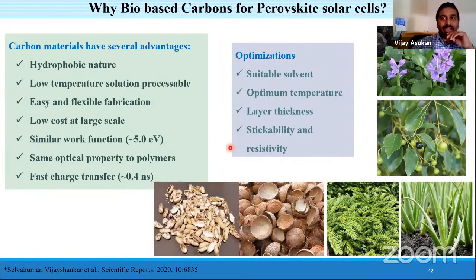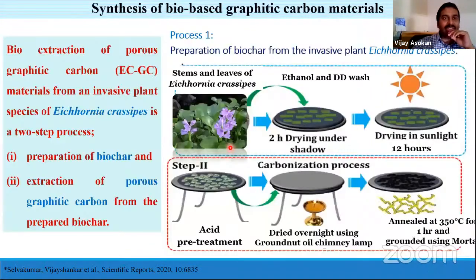So you can do many optimizations when we are synthesizing. Of course, we tried to get a bio extraction of porous graphitic carbon. We named it ECGC, because it is obtained from Eichhornia crassipes. We prepared biochar in the first process, then extracted porous graphitic carbon from the prepared biochar. So it's a two-step process, shown here, and you can see this in detail in Scientific Reports, published in 2020.